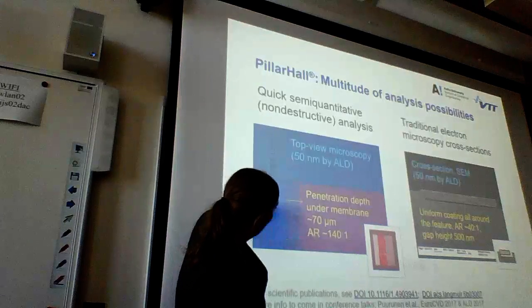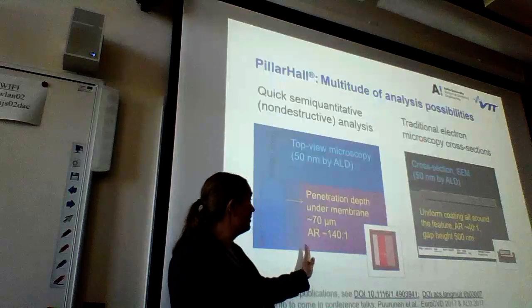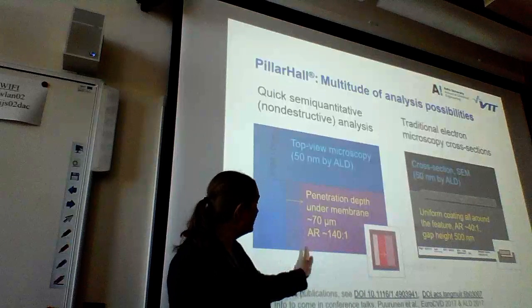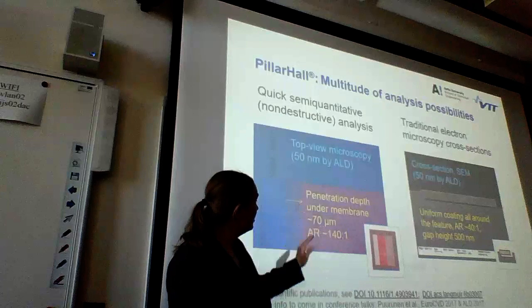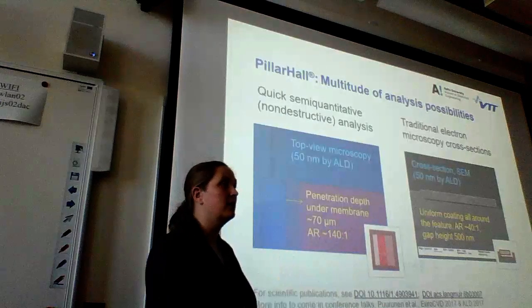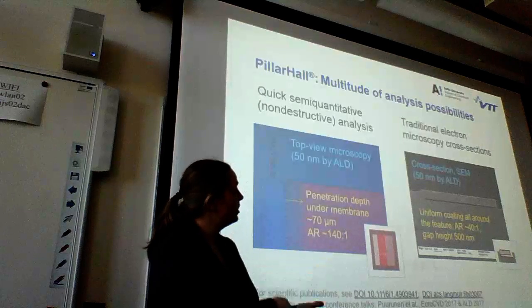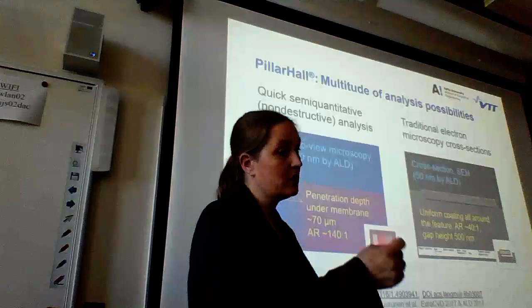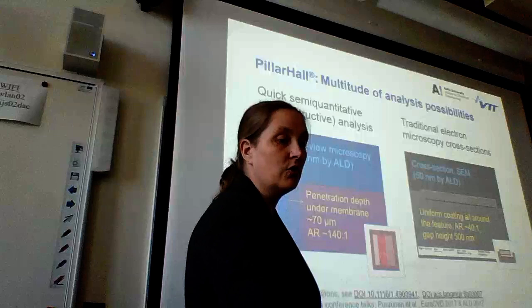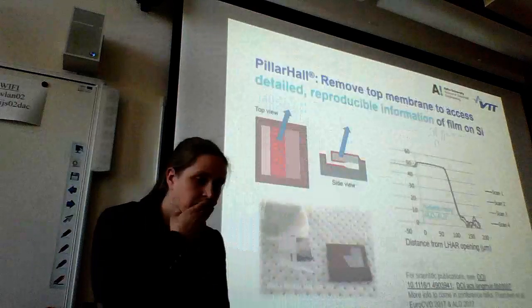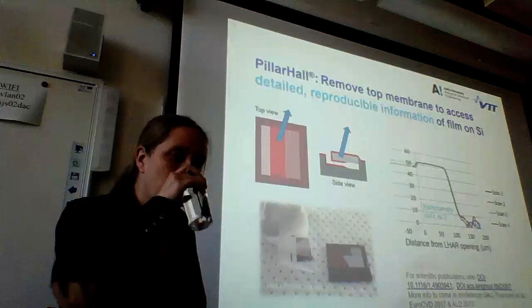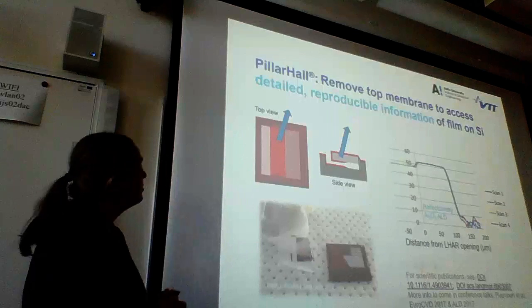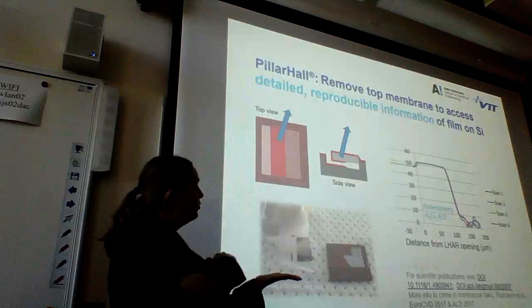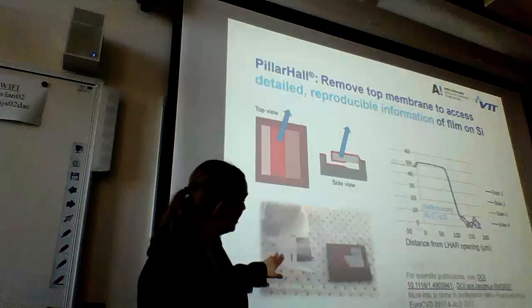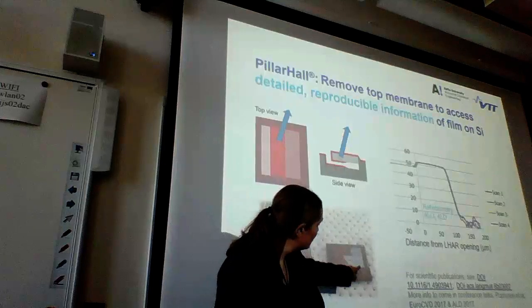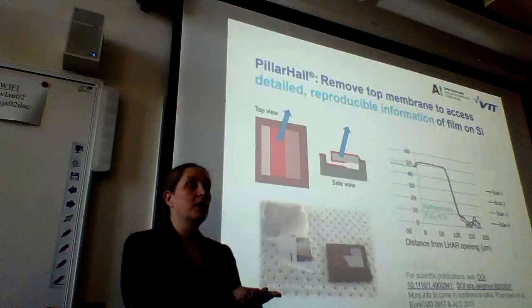And here under, the film goes in, and then you can, for example, just by regular visible light microscopy, in some cases see how deep it goes. You can see the pillars and you know their distances, so you can actually very quickly say that it went 100 micrometers or something else. Of course, you can also cut them in half and investigate with electron microscopy, just like the vertical ones that people normally are used to looking at. Where things get really interesting is if you remove the roof and you expose the film. Like here we have removed the membrane just with regular adhesive tape, and then you expose the film directly on silicon.